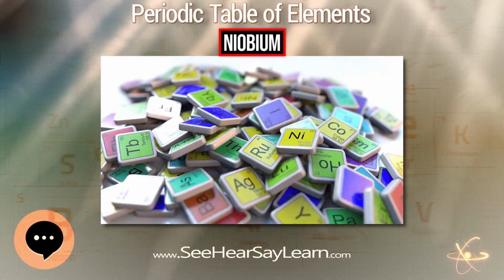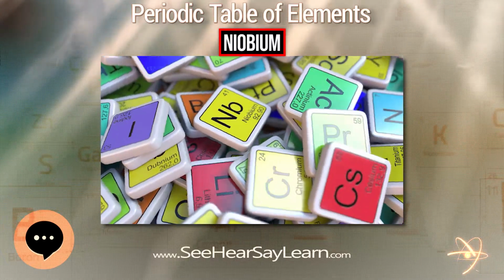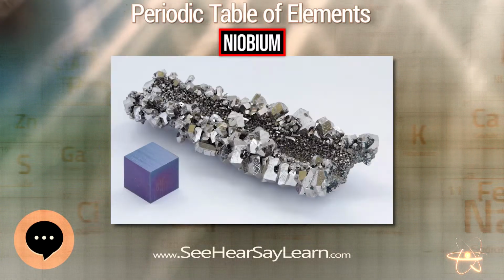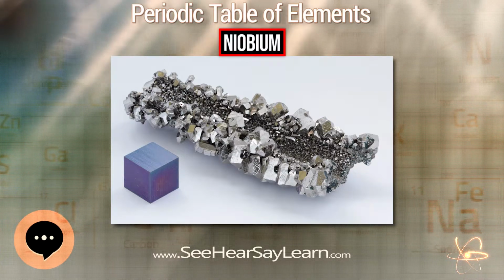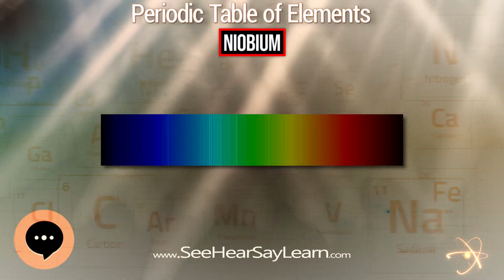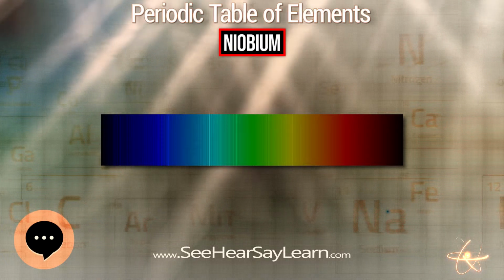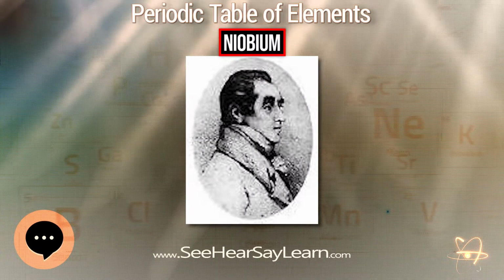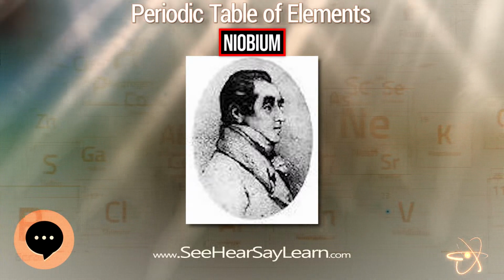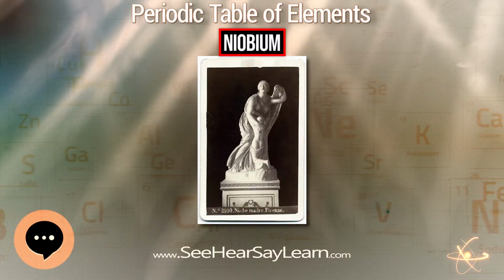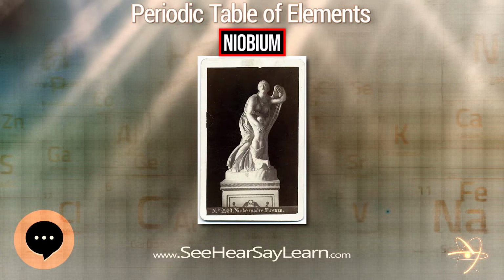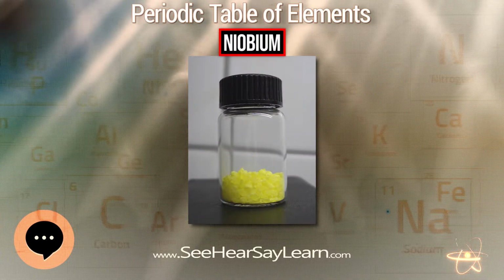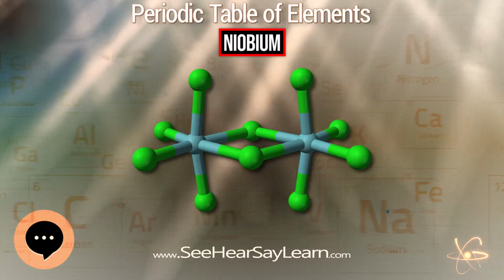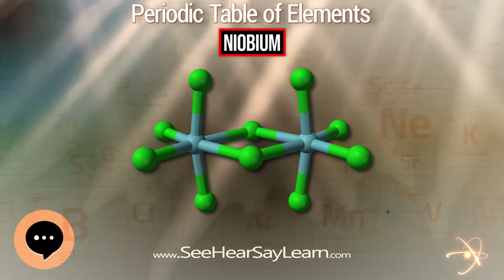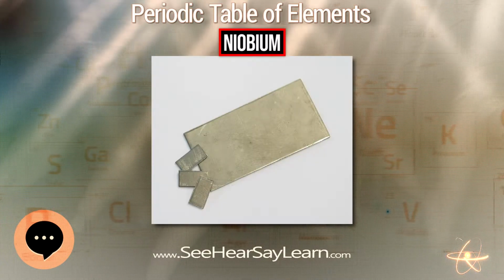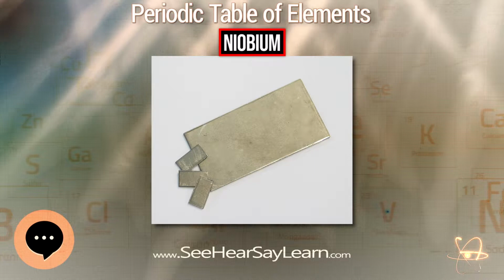In the aluminothermic reaction, a mixture of iron oxide and niobium oxide is reacted with aluminium. Small amounts of oxidizers like sodium nitrate are added to enhance the reaction. The result is aluminium oxide and ferroniobium, an alloy of iron and niobium used in steel production. Ferroniobium contains between 60 and 70% niobium. Without iron oxide, the aluminothermic process is used to produce niobium. Further purification is necessary to reach the grade for superconductive alloys. Electron beam melting under vacuum is the method used by the two major distributors of niobium.